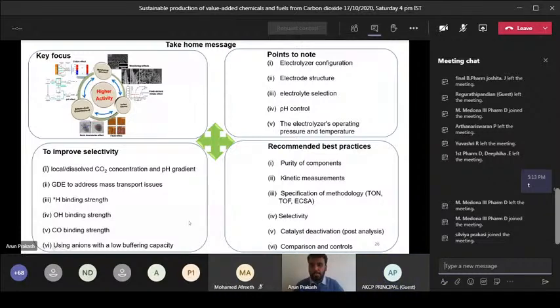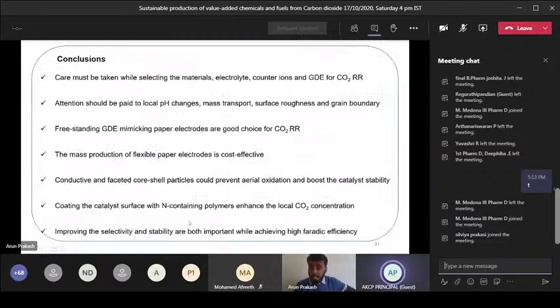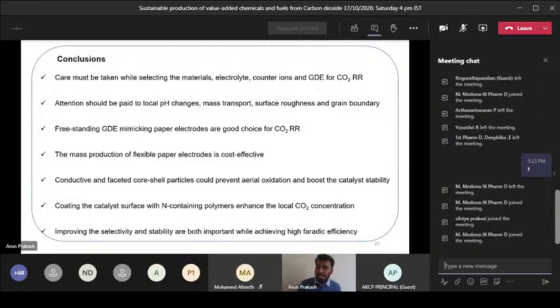And conclusion. This is the take-home message for you all: care must be taken while selecting the materials, electrolyte counterions, and GDE for CO2 reduction. Attention should be paid to local pH changes, mass transport, surface roughness, and grain boundary. Freestanding GDE is much more efficient than the normal bulk electrolyte and is a good choice for CO2 reduction. Mass production of flexible paper electrodes is cost effective.